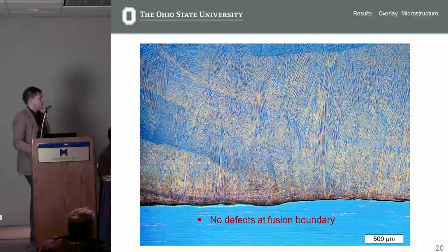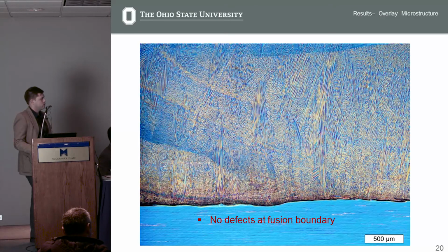Overlay macrostructures at the fusion boundary revealed no defects at the fusion boundary, no solidification cracks, which was the primary motive for this investigation, and also no lack of fusion, despite the CMT process being perhaps a misnomered cold process. It is a cold process with respect to pool, but we can see here that no lack of fusion defects because of that occurred.